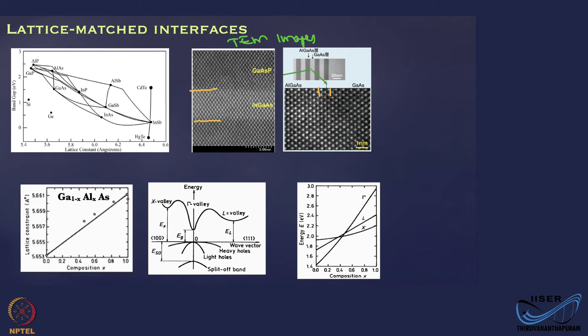If you ignore that those are made of two different sets of material elements, and just assume that those are all lattice points, they're just continuous. There is not much mismatch between this system and that system. That means the lattices of these two materials are so identical that there is a perfect lattice-matched interface. Similarly here, this is a gallium arsenide, aluminum gallium arsenide interface. In this case also, as you draw a line from here to here, it's perfectly periodic. There are no defects, there are no dislocations. These are real images of these materials between these two systems. The perfect lattice match.